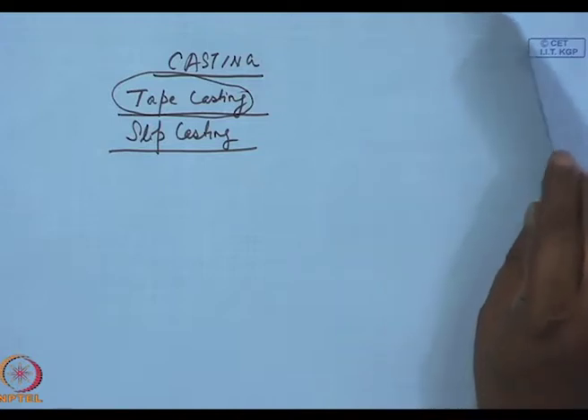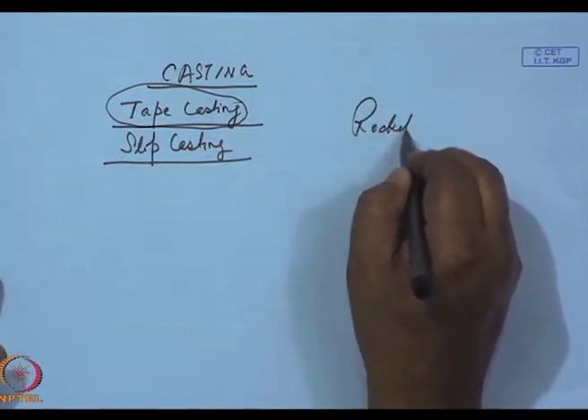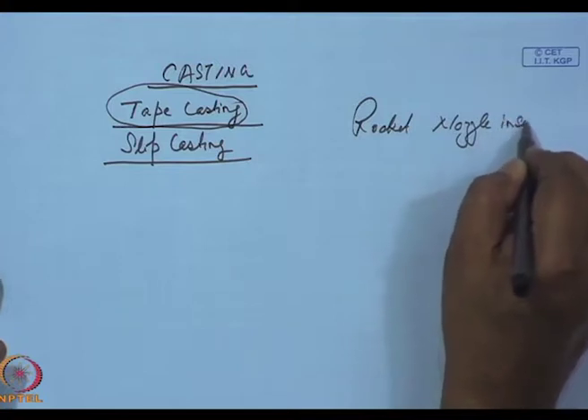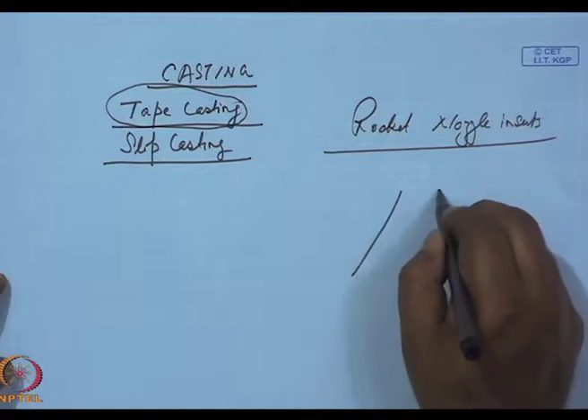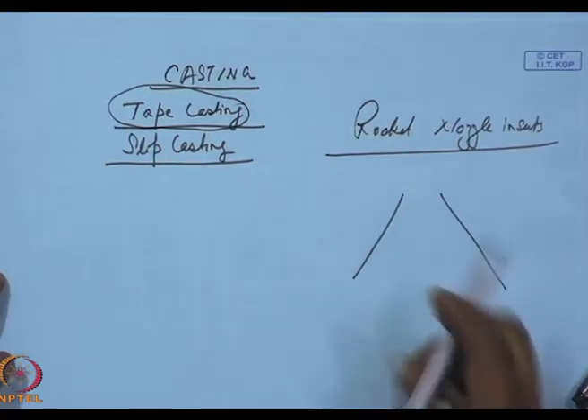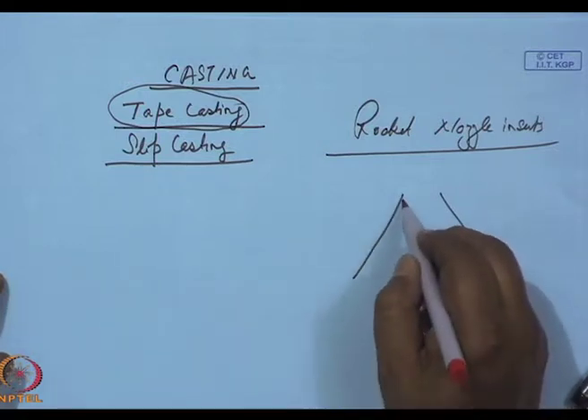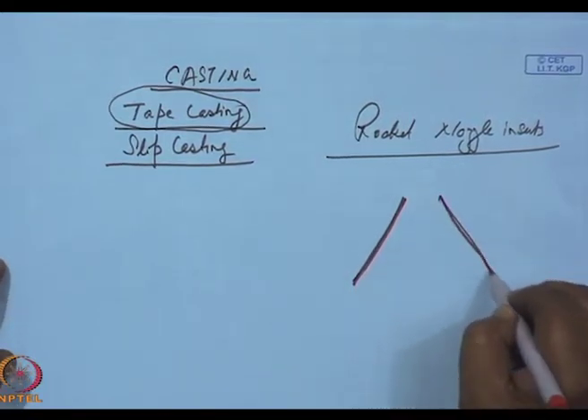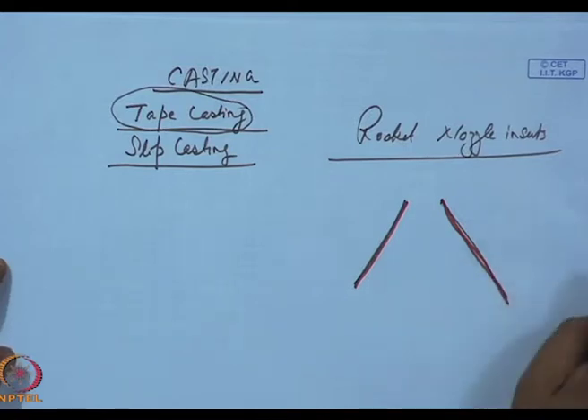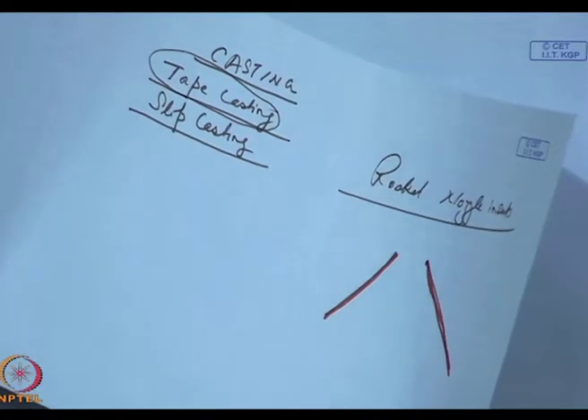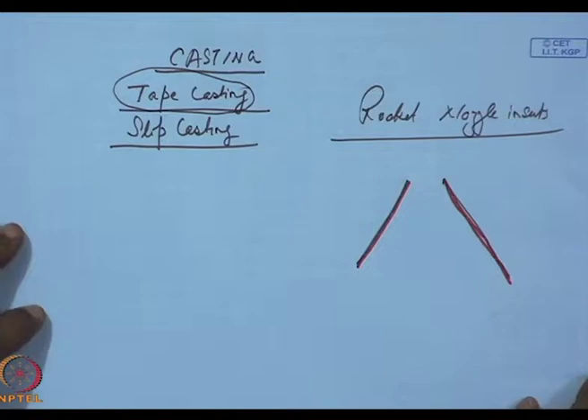Why? You see, by tape casting, if I can get ceramic tape like this, what I can do is I can make it, fold it, and these are used as rocket nozzle inserts. When the rockets fire, this is the metal. What protects the metal from the searing heat of the gas flames, whose temperature can rise to 3000 degrees centigrade? Here there are ceramic inserts which protect the rocket nozzle, and that comes from ceramic tapes of such thicknesses which are tape cast and then used as rocket nozzle inserts.